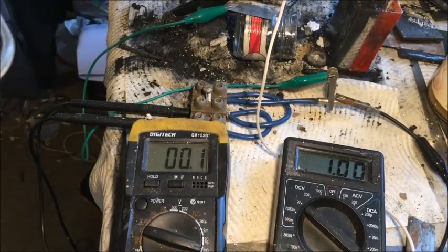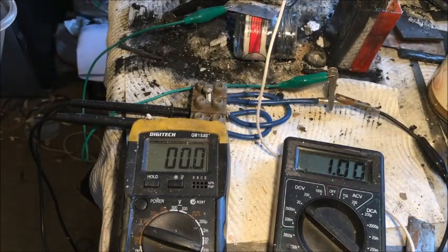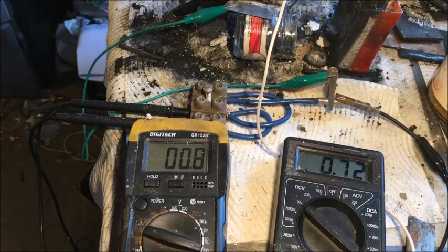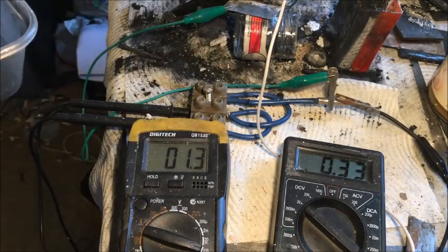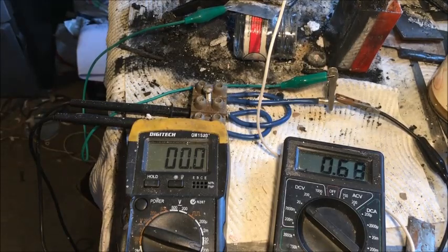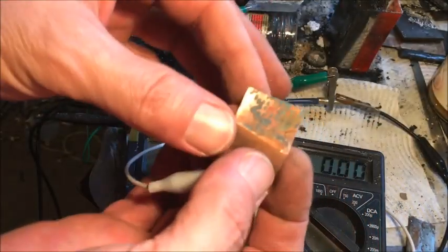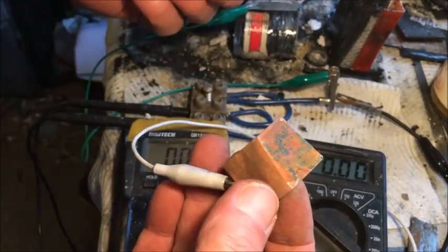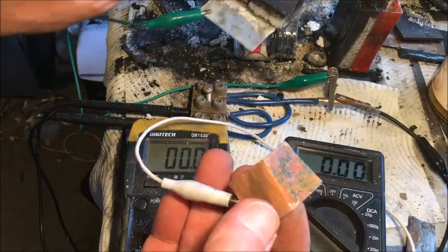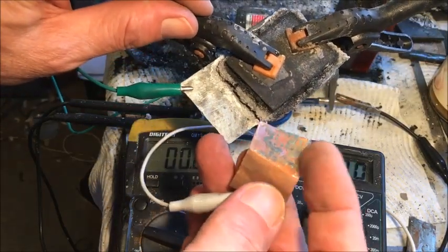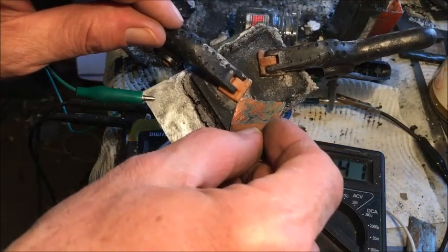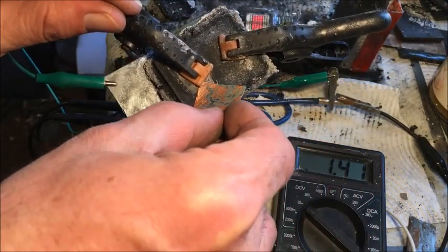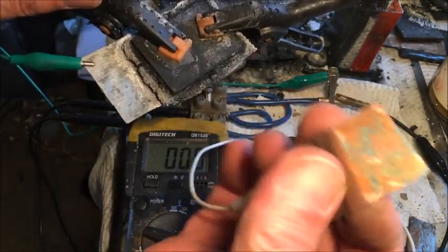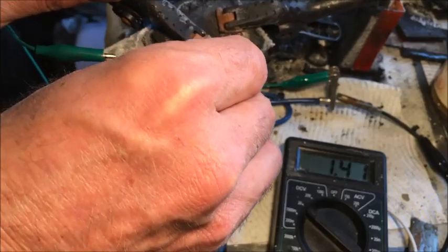It's at 1 volt. Nothing special, but it's sort of semi-dried out. And 2 milliamps just, and dropping fast. Could be the contact's gone again under that plate. We'll just check that while we're here. Yeah, the contact, and I kept that clean. I think it does come through the graphite pad somewhat. So I guess if I clean that off, we'll probably go back up to 1. Oh look, just touching it there like that, we got 1.4 volts. So yeah, cleaning the copper contact definitely increases the voltage of this cell.